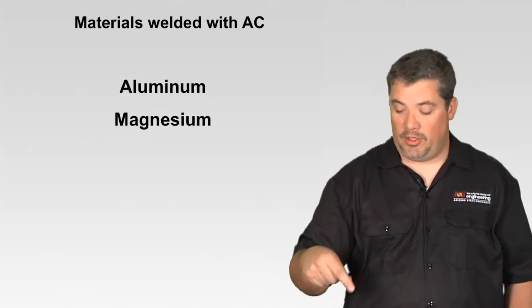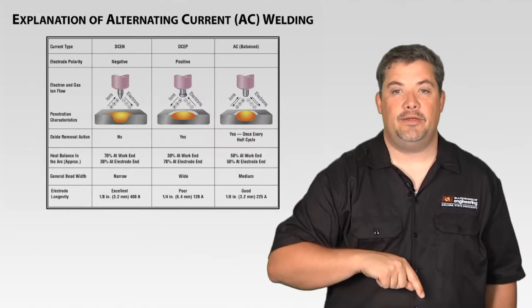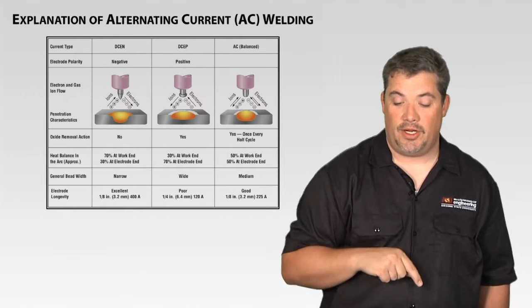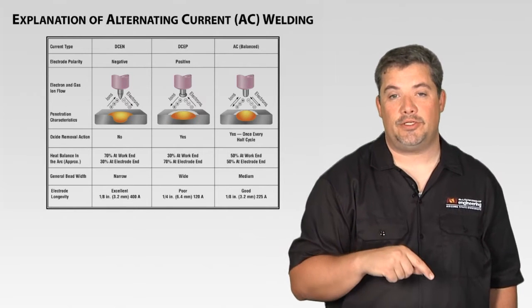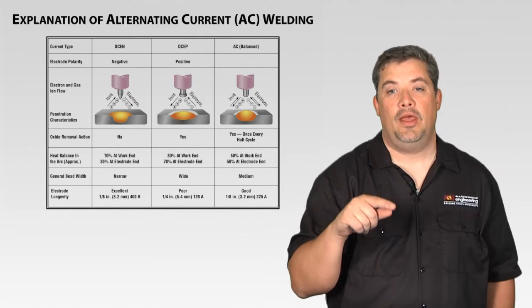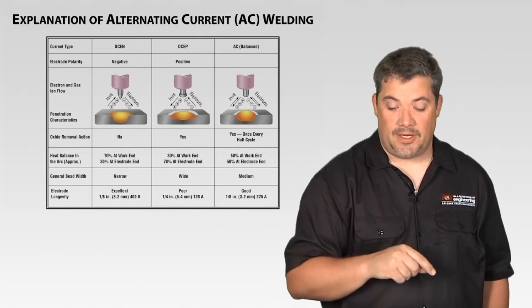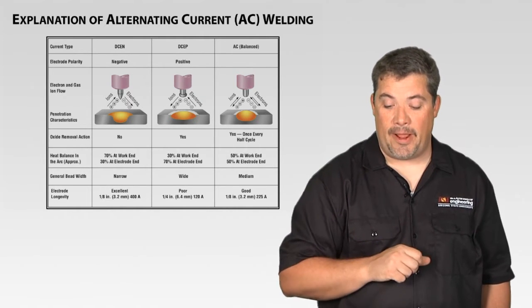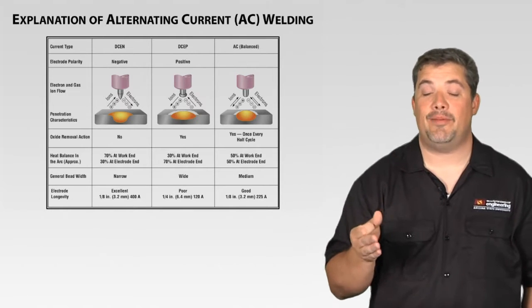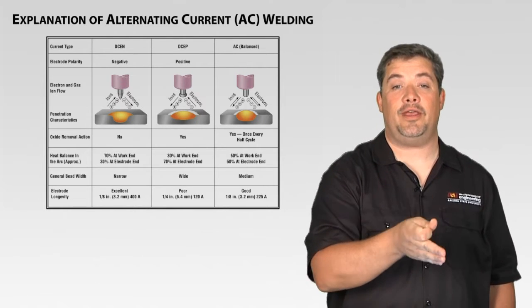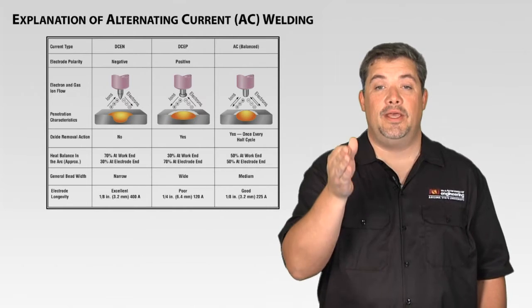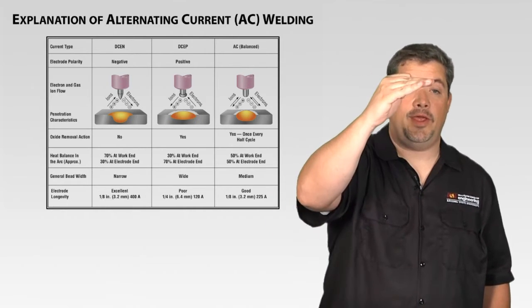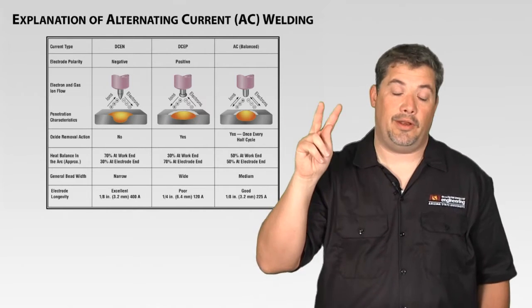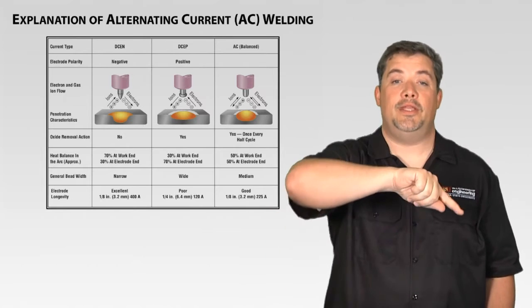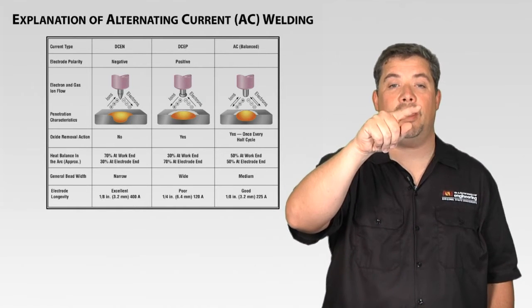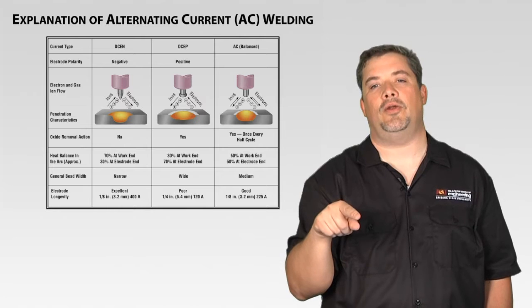So materials that are welded with AC, as we mentioned before, are aluminum and magnesium. And this chart right here is what you're going to want to remember. You're probably going to want to take a screenshot because you're going to see this again. The important stuff here is in the AC balanced column. When we say balanced, that means half the cycle time is electrode negative, the other half is electrode positive, and they're both hitting the same amperage level. So if I was welding at AC 100 amps, half the time it's negative at 100 amps, half the time it's positive at 100 amps.